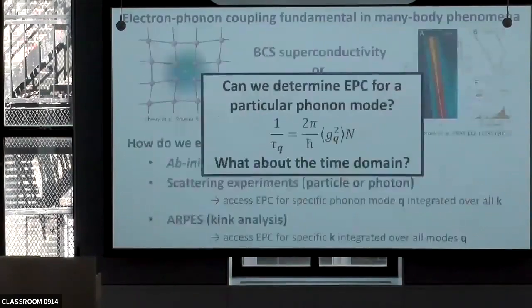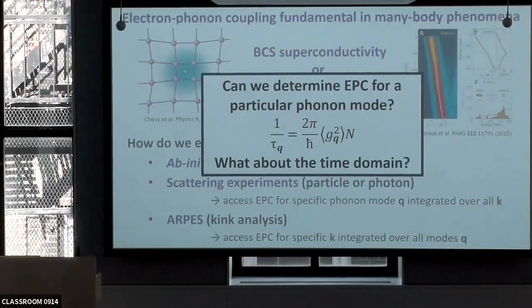So the question then is, can we do it in the time-resolved mode? And in particular, instead of looking at lambda, can we look at something more fundamental? Can we look at the matrix element squared for electron-phonon coupling for a specific Q? And can we possibly do it by extracting it through the electron-phonon scattering time that is directly related to it?